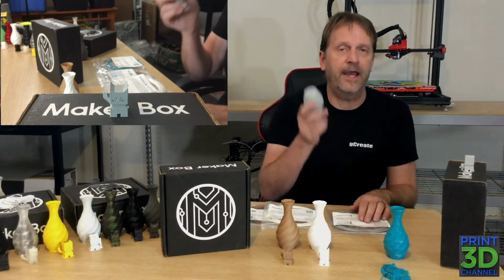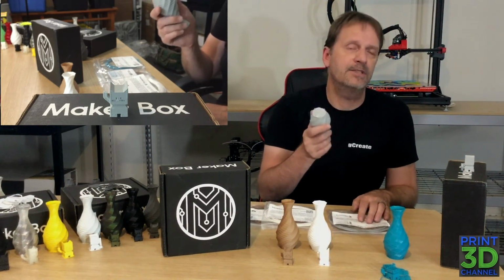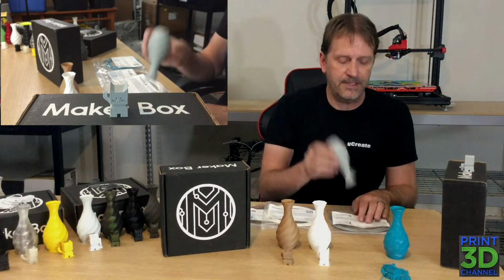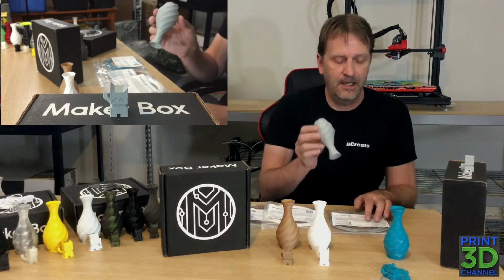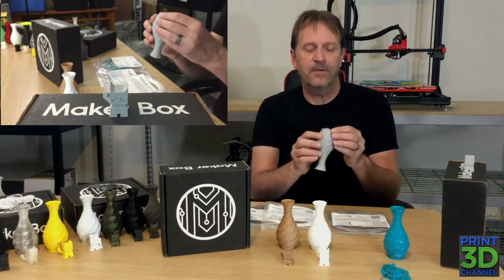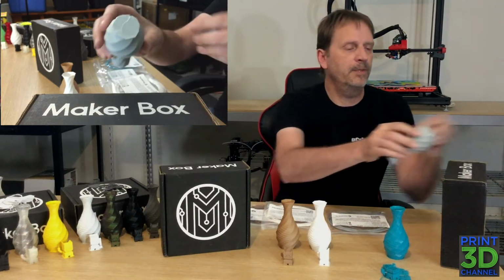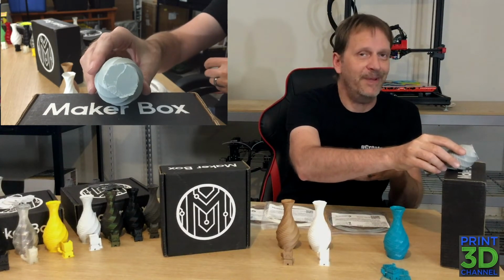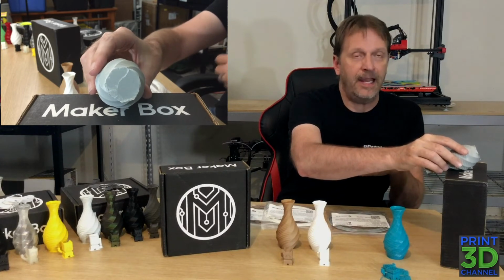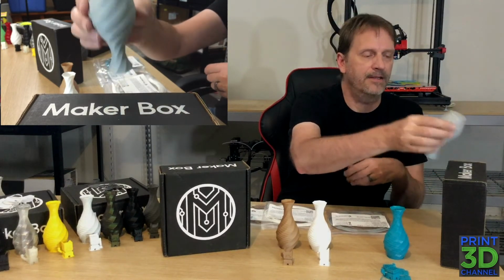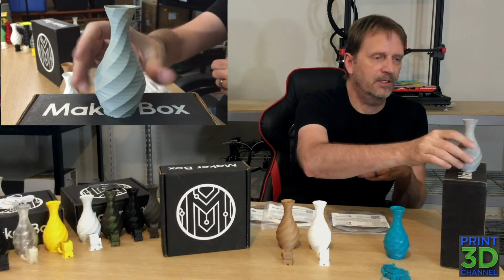So I printed mine out at 230 C, and I only used 80 C on the bed because I didn't want to go all the way up to 110 C, and I'm glad I didn't, because even with a little bit of Magigoo, this pretty much fused to the glass bed with the Magigoo at 80 C, 230 C on the hot end. So I'm just going to leave that there because the rest of the print looks really good.